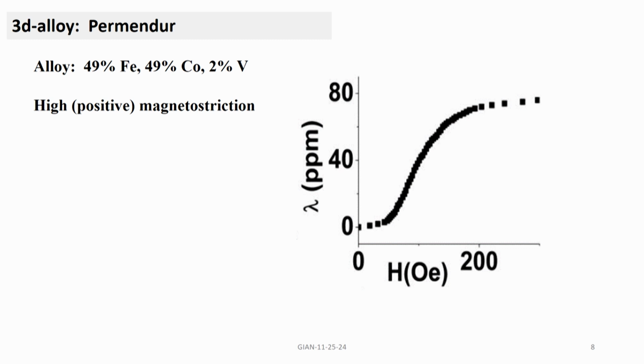So, the alloy, we will discuss several composites with permendur. It has 49% iron, 49% cobalt, 2% vanadium. It has good magnetostriction, but in the previous case for nickel it is negative, for permendur it is positive. It can be as high as 80 parts per million. Now, also permendur has very high permeability.